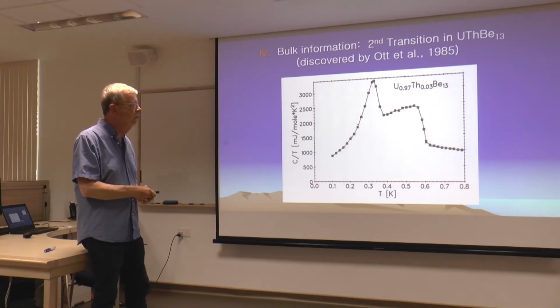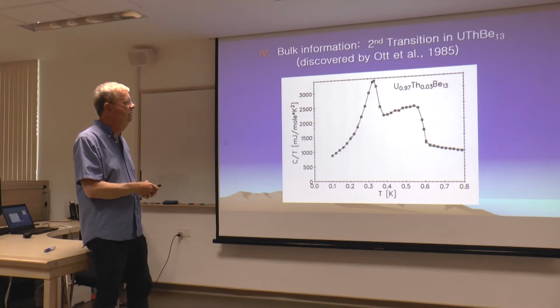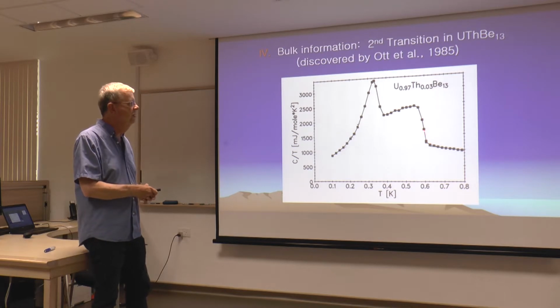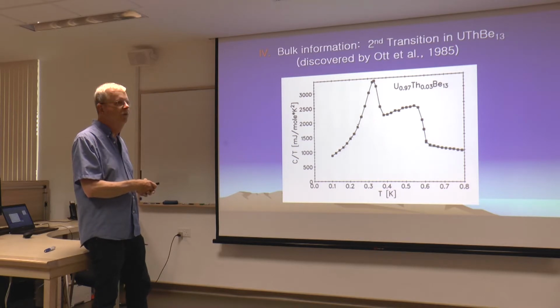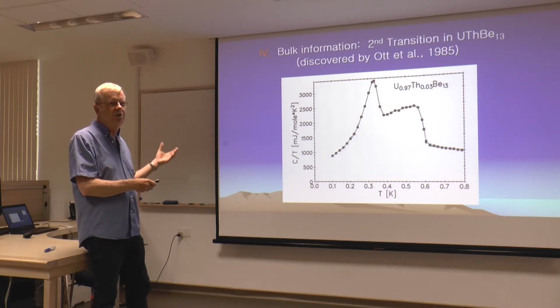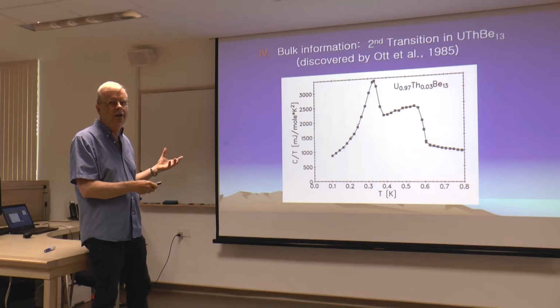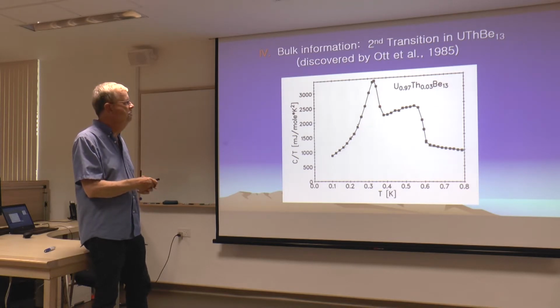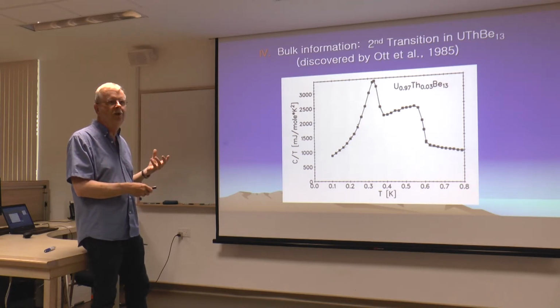it's something you need to prove that this is superconductivity. This sees a Meissner effect. This sees the resistive transition go to 0. And this temperature also sees a magnetic susceptibility that says it's diamagnetic. But when you get to here, the resistivity is already 0. So you can't measure the resistivity down at 0.4 Kelvin and see a second transition. 0 is 0. It's been shorted out. The specific heat has a transition, but how do I know that's superconductivity?